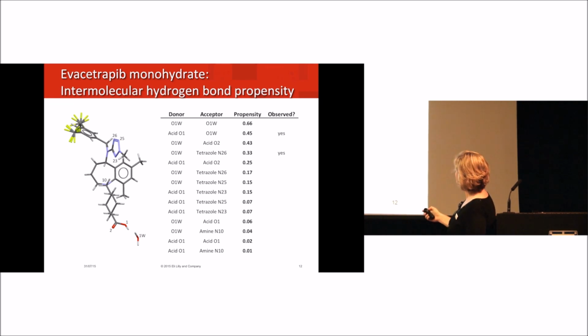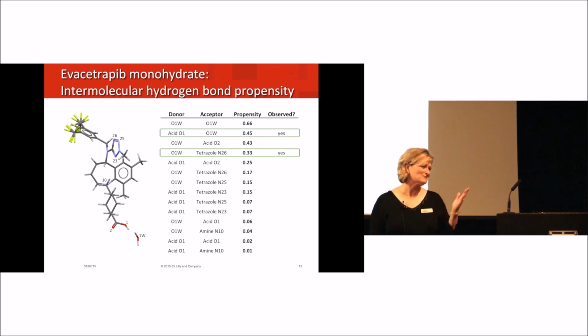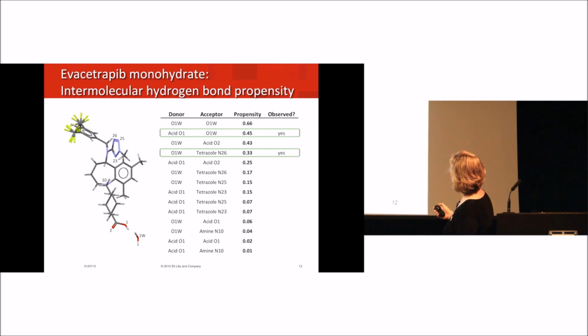In terms of the hydrogen bond propensity, one of the things that we found really interesting is water actually probably preferred interacting with itself. That was kind of interesting. But generally speaking, we had reasonably high satisfaction of the hydrogen bonding groups.